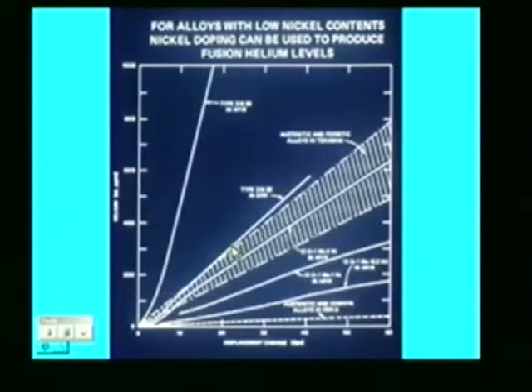There's another technique. If we have some alloys with low nickel contents, we can increase the nickel by nickel doping to produce the correct helium to dpa level. And here we're looking at an alloy. I hope you can read it better than I can. It's a common alloy of 12 chrome 1 moly with 0.2% nickel. If we irradiate that, we get far below the desired cross-hatched region, but if we can increase the nickel to 2%, we can produce the desired amount of helium.